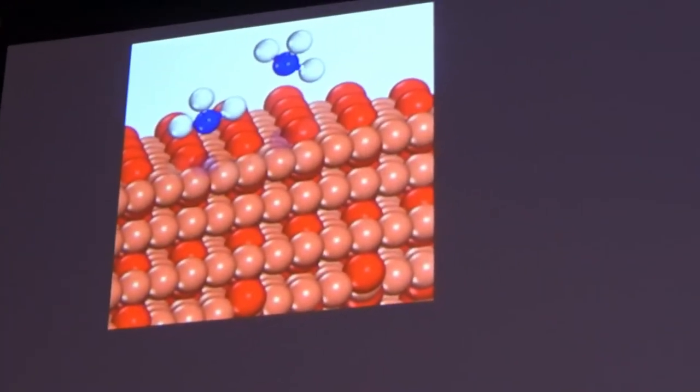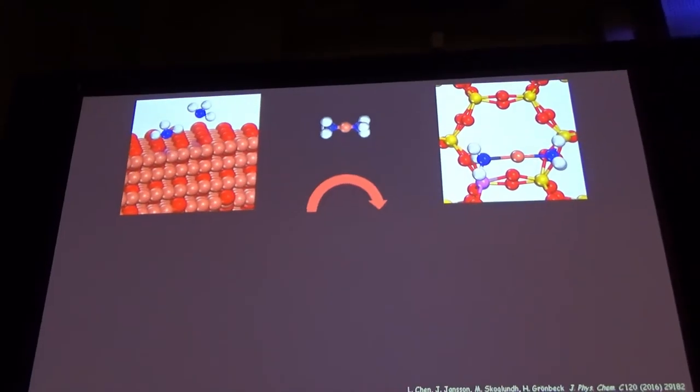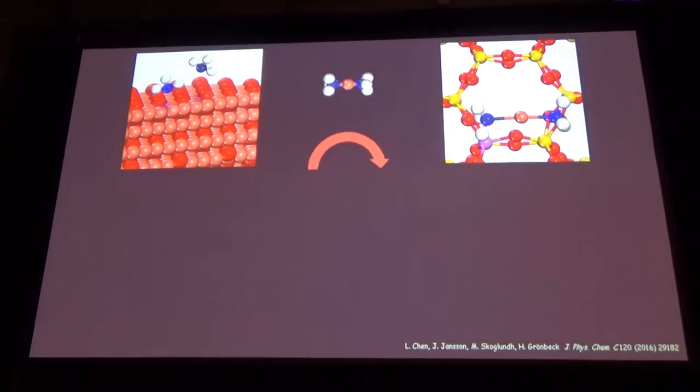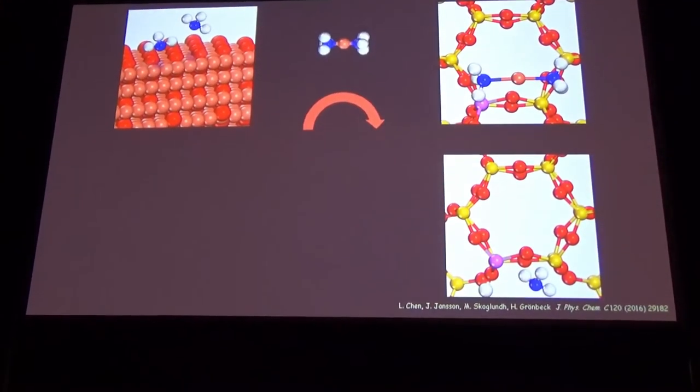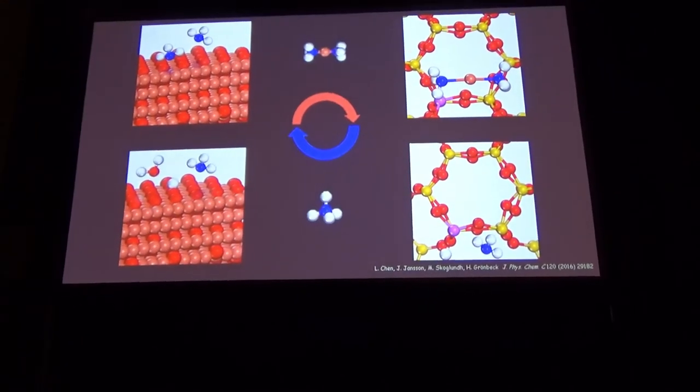The take-home message: we start with the copper oxide surface, two ammonia molecules interact with the surface and form a diammine complex, which then diffuses with low barriers into the zeolite structure where it is almost unaffected in bond angle and bond distances—showing weak adsorption. The proton is taken up by ammonia acting as a proton carrier, which takes the proton out to the copper oxide surface where hydroxyls can form and eventually water.